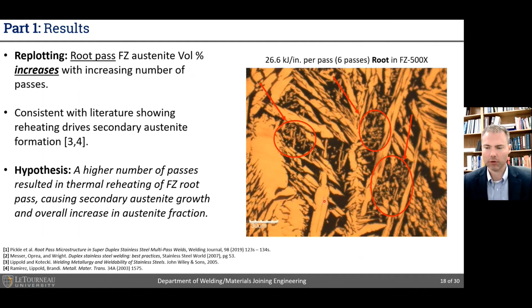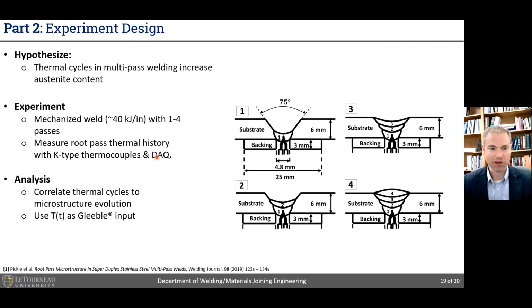So zooming in and looking at one of these 6-pass welds that have the higher austenite content, we can see these small and very prevalent amounts of intergranular secondary austenite formation. And so this led us to make the following hypothesis, that a higher number of passes are resulting in thermal reheating of the fusion zone root pass, which is causing the secondary austenite growth and overall increase of austenite volume fraction. So to test this hypothesis, we wanted to really dig into it, and so we designed the following set of experiments.